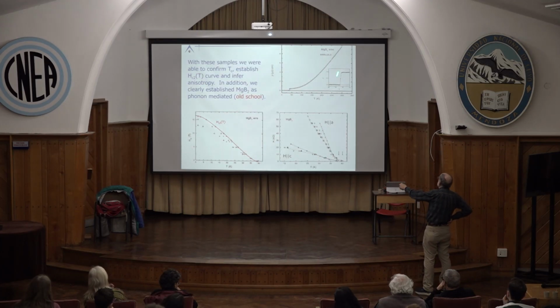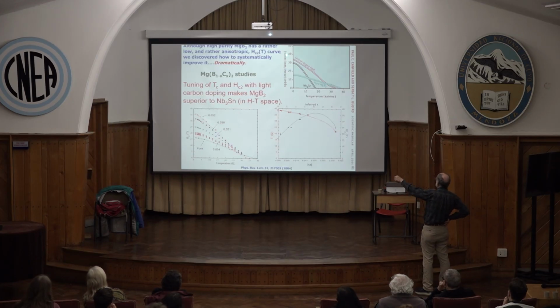Okay? And we could confirm TC. We could establish HC2. We even came up with a clever way for polycrystalline materials how to infer the anisotropic HC2. Okay? But more importantly, if you look at the niobium 3-tin, pure MgB2 looks like it's disappointing. It's only going to 15 rather than 30. But this is very pure MgB2, and we figured out if we doped in a small amount of carbon, we could add 1, 2, 3, 4, 5%. We could get above 35 Tesla. So bulk carbon-doped MgB2 has an HC2 curve that supersedes niobium 3-tin.